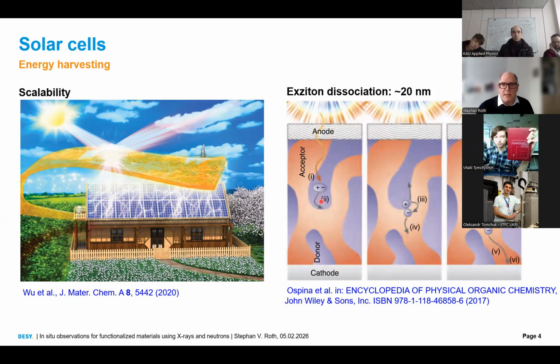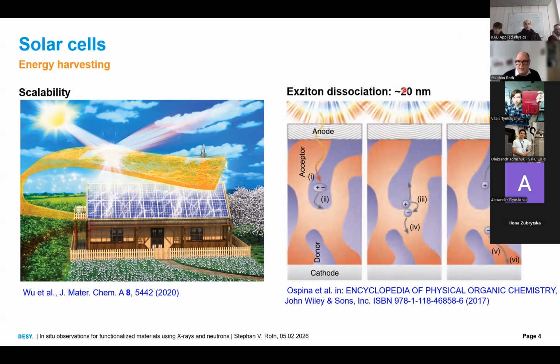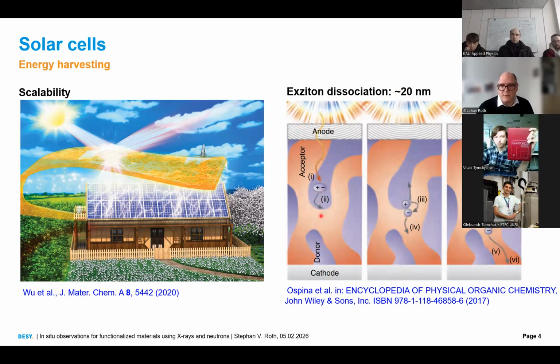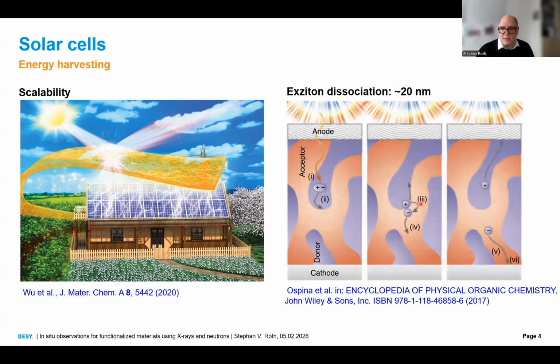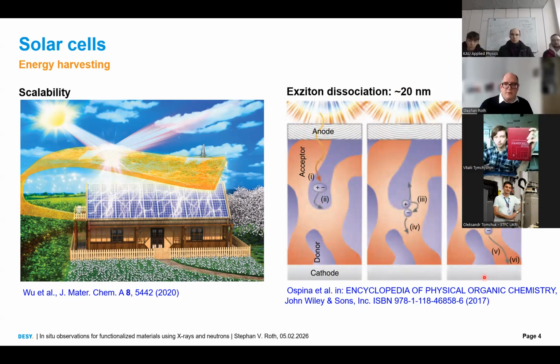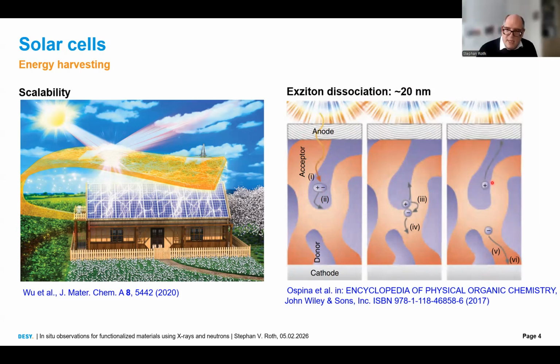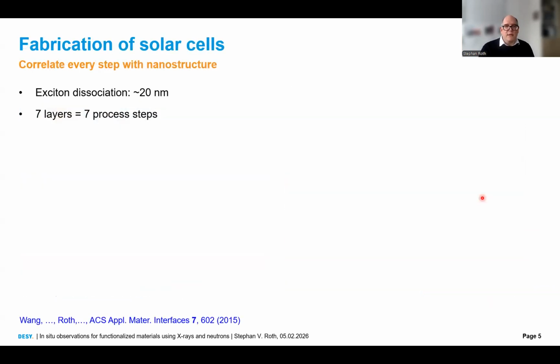The solar light creates an exciton. The exciton diffuses about 20 nanometers before it dissociates at the interface. The charges are separated and then go to the corresponding electrodes. And the mechanism of establishing this photoactive layer, the electrodes and their combination, this is the typical area of research we have.